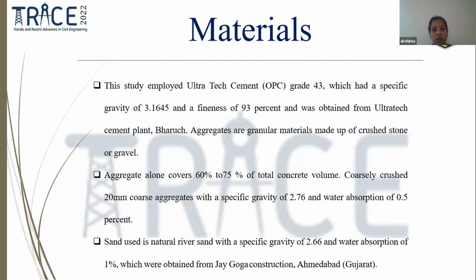Aggregates are granular materials made up of crushed rocks. Aggregates alone cover 60% to 75% of total concrete volume. Coarse crushed aggregate of 20 mm is used, with a specific gravity of 2.76 and water absorption of 0.5%. Sand used is natural river sand with a specific gravity of 2.66 and water absorption of 1%, obtained from Jay Goga Construction, Ahmedabad, which transports the sand and other materials to sites nearby.